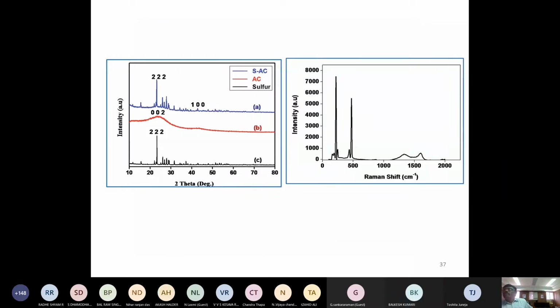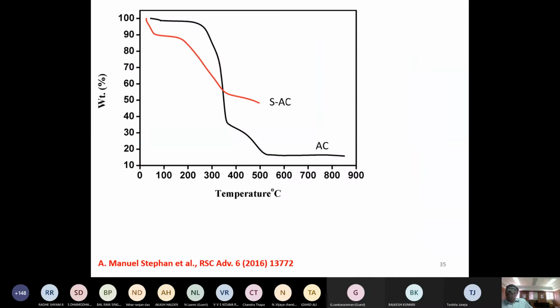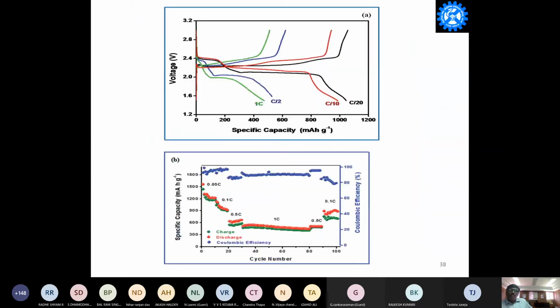We confirmed the presence of sulfur by XRD and also Raman. Then 50% of the sulfur was impregnated, which was measured from the TG, thermogravimetric analysis. We used the cathode for lithium sulfur batteries, and we charged and discharged at different C rates. For example, at C by 20, we got more than 1050 milliampere hour per gram, and when we charged and discharged at a faster rate, the capacity was reduced to 500 milliampere hour per gram. We were able to cycle this system for only 100 times. After that, we could not get good results.